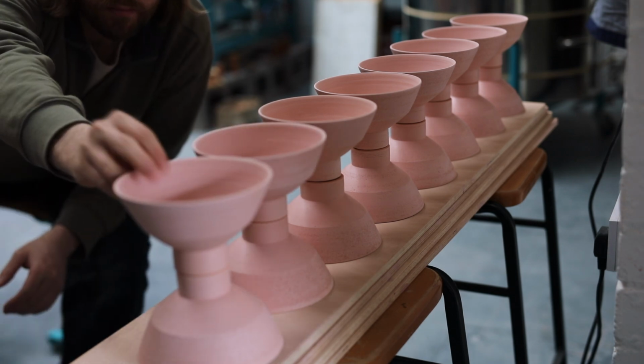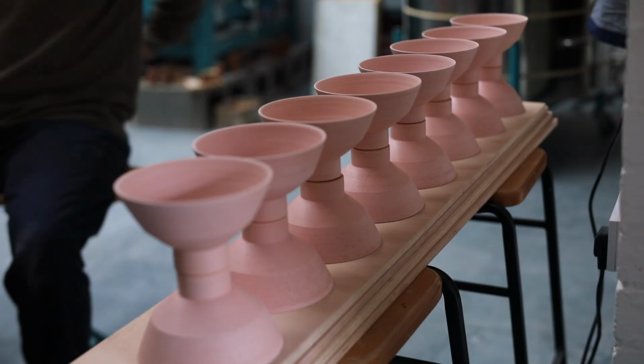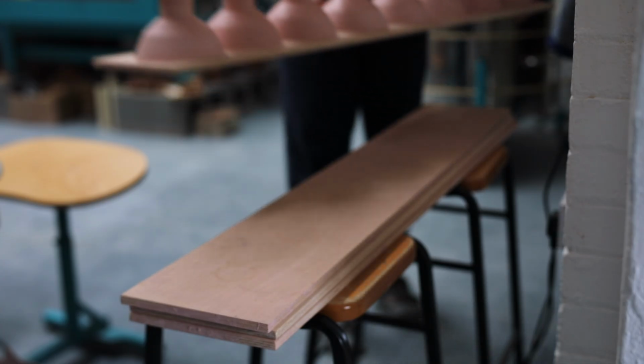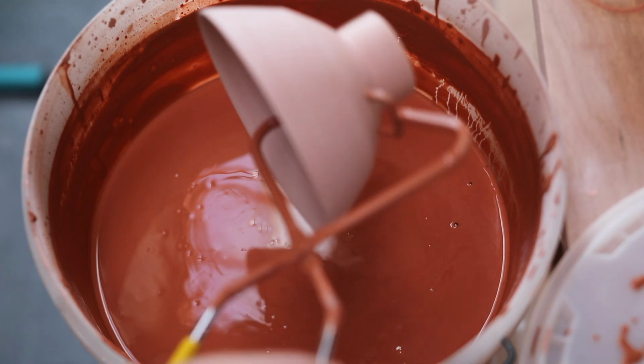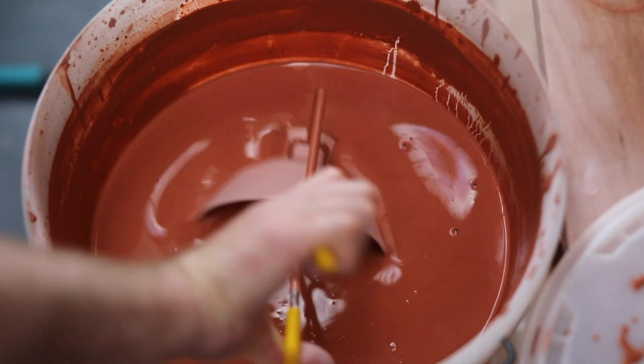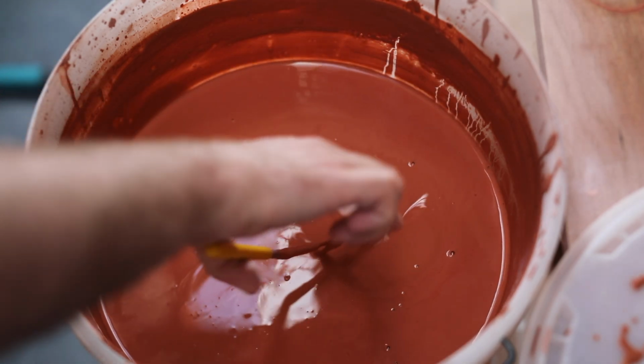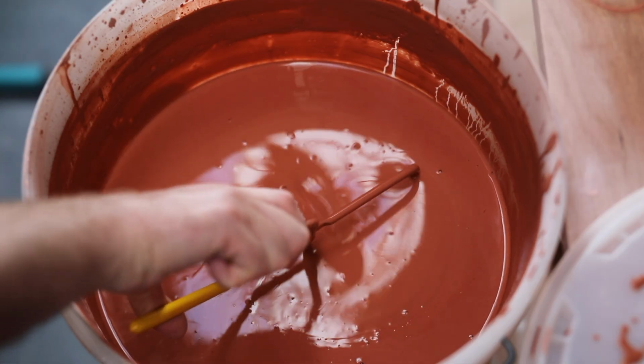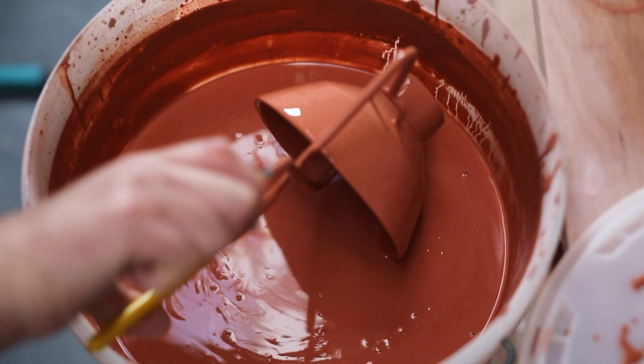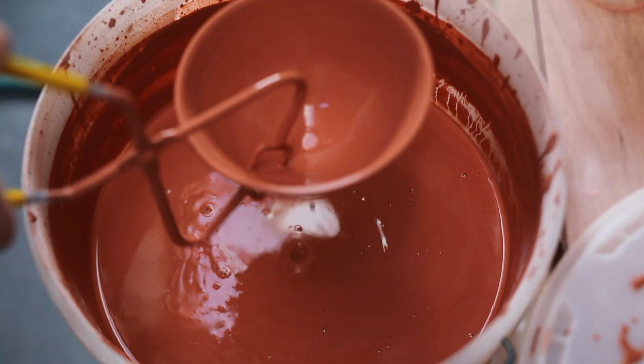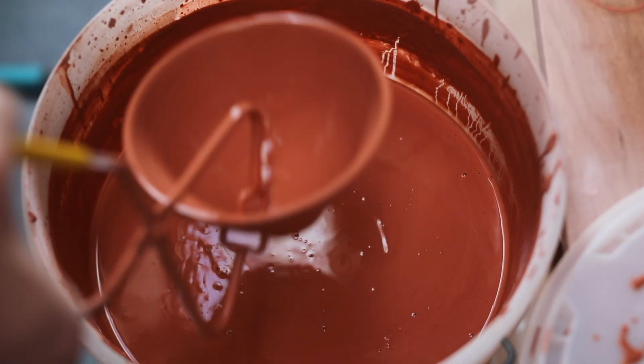At this point I sort of lost the bowls within all the others, but they should be fairly easy to identify, as the bronze creates these small black dots on the pots at this stage. I then dipped each of these pieces into a pale green feldspathic crackle glaze, submerging it for about 3 or 4 seconds before drawing it out, flipping it the right way up and catching glaze on the inside, which I can then swirl about into an even layer.